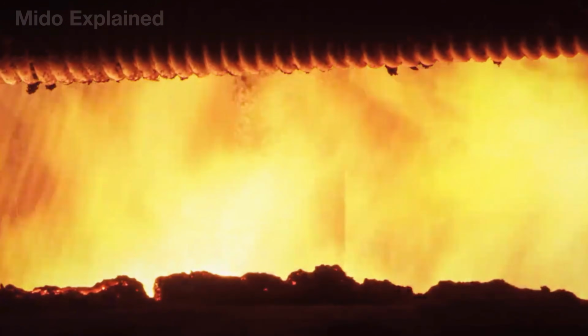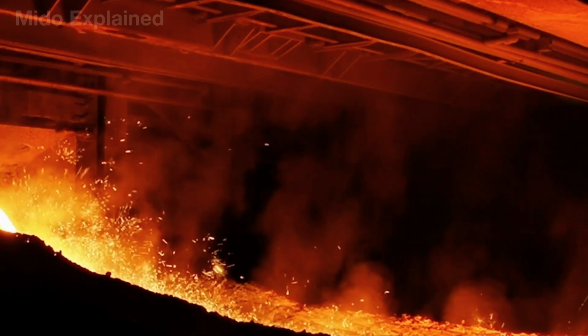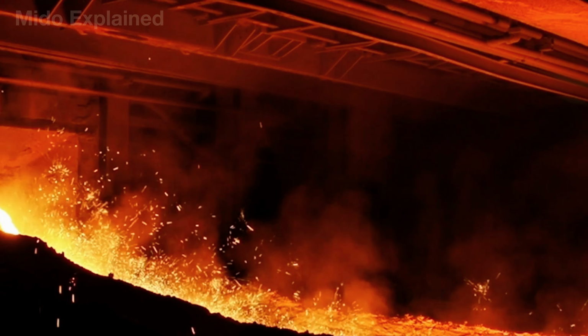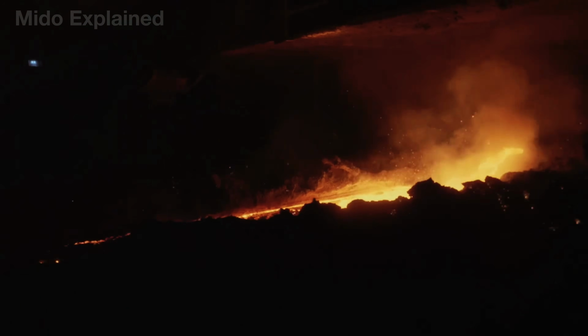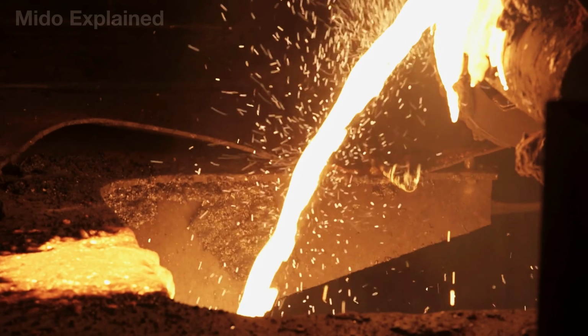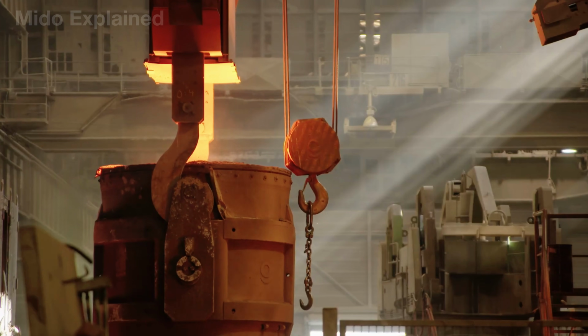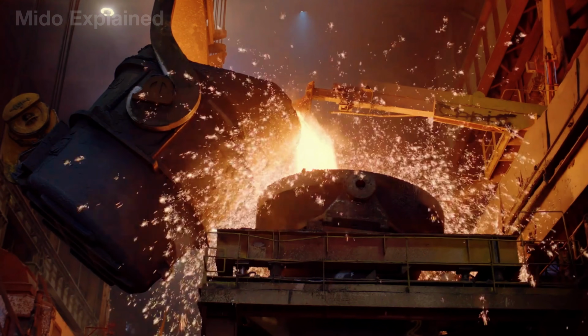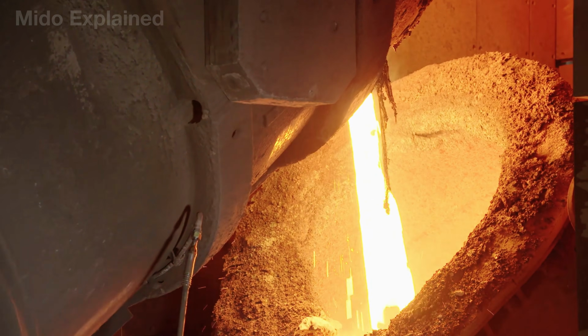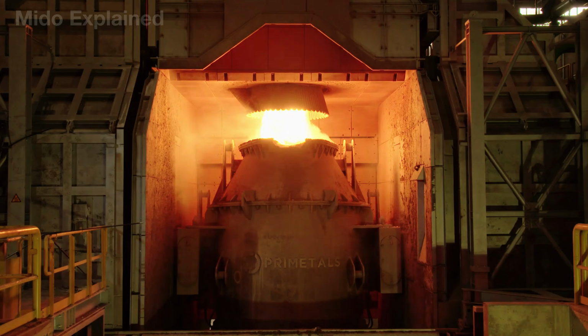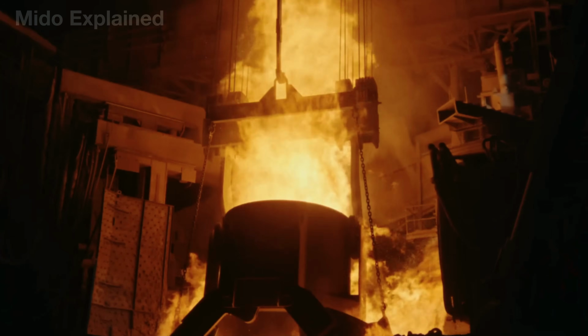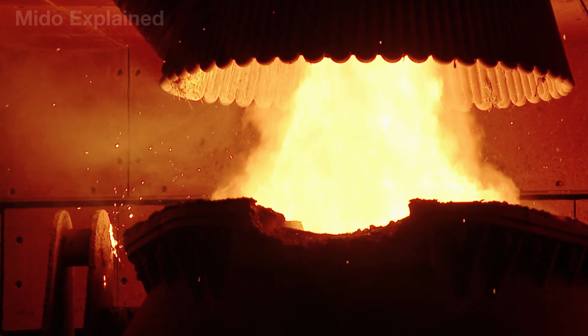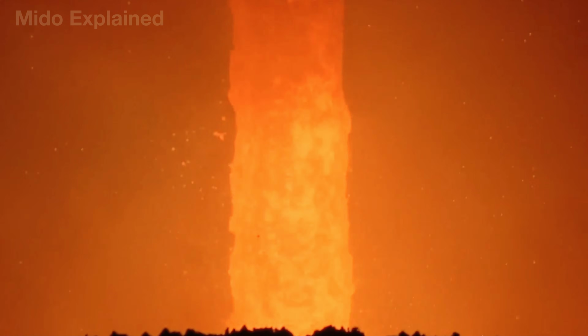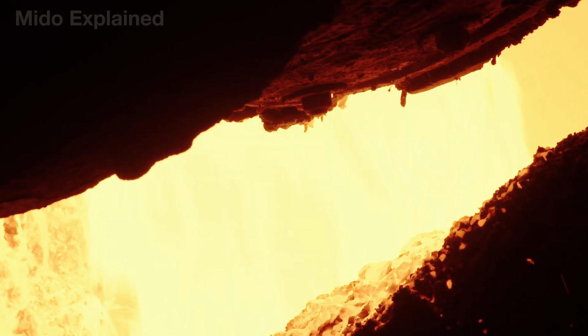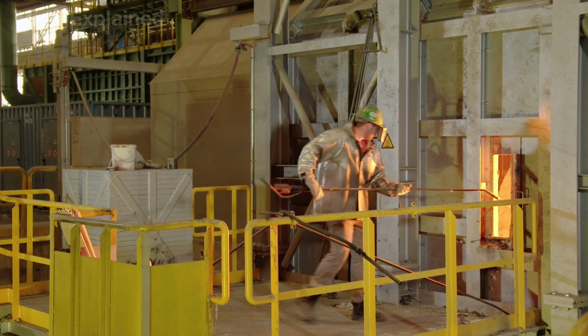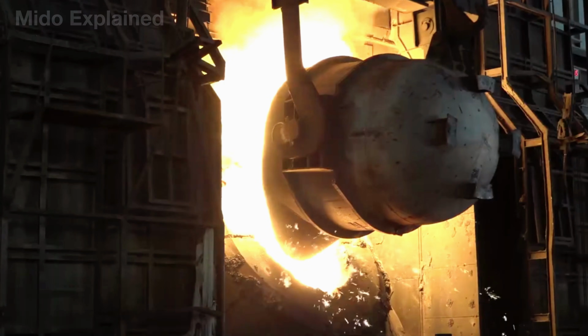After leaving the electric arc furnace, molten steel is not yet stainless steel because its chemical composition does not yet meet the stringent requirements of stainless steel. That's why the molten steel is transferred to a special device called an AOD converter, short for argon-oxygen decarburization. From the outside, the AOD looks like a giant steel vessel that can hold tens to hundreds of short tons of molten metal. When the process begins, a mixture of oxygen and argon gas is blown into the molten steel through nozzles located at the bottom of the furnace. This allows carbon to be reduced to extremely low levels while most of the chromium is retained.